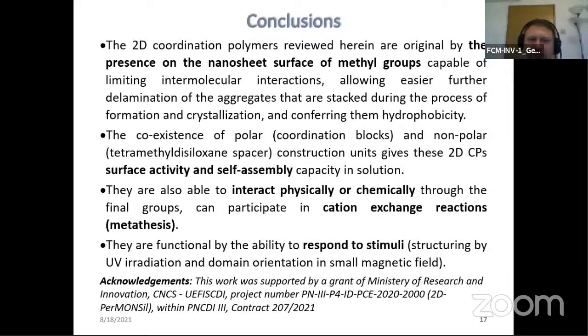In conclusion, the presence of methyl groups on the nanosheet surface limits the intermolecular interactions and allows easy delamination of such aggregates. The coordination polymers that we synthesize have surface activity and can self-assemble in solution. These coordination polymers can interact through their end chain groups and side groups and also participate in cation exchange reactions and metathesis reactions, and can respond to multiple stimuli such as ultraviolet light and magnetic fields.